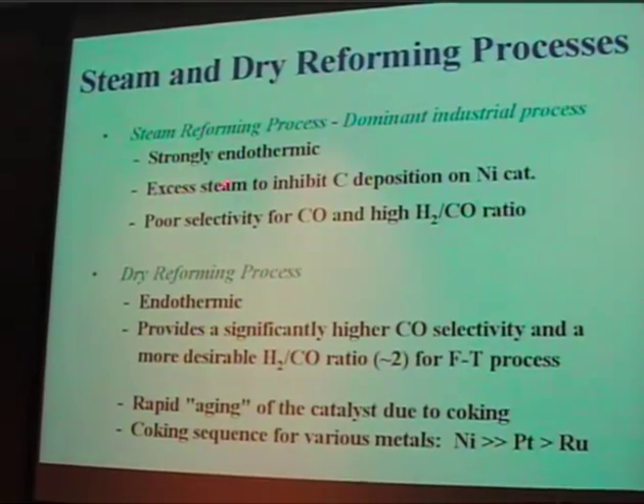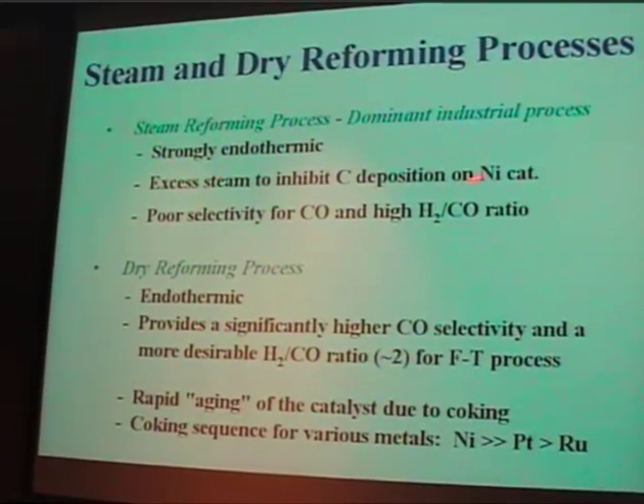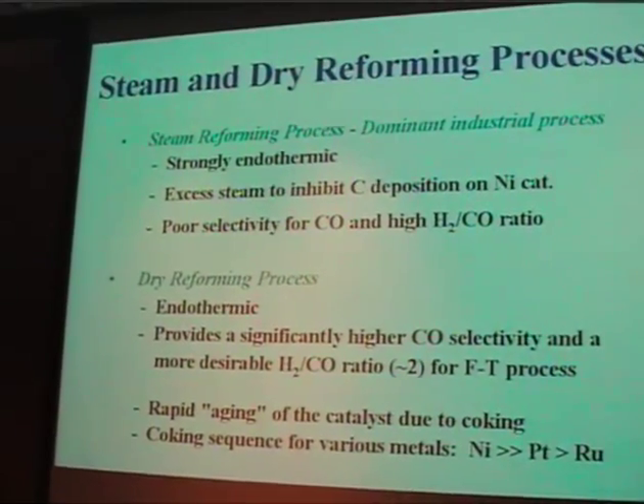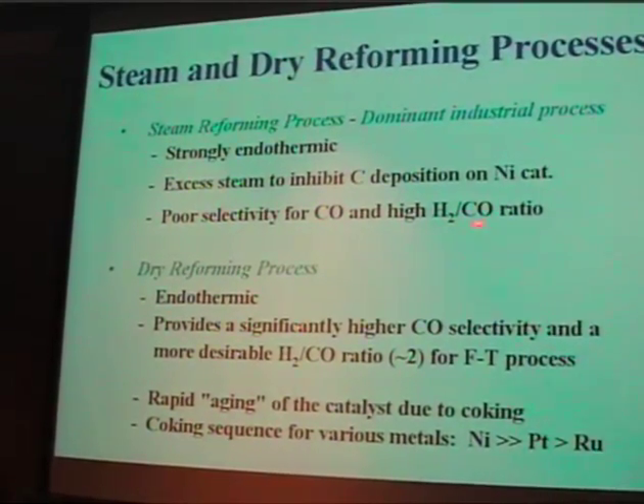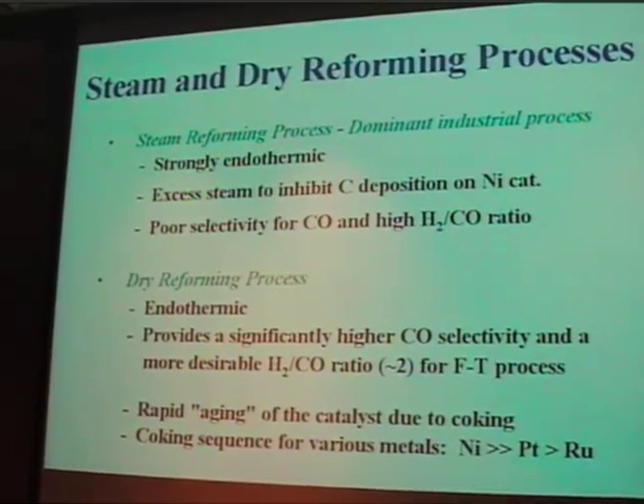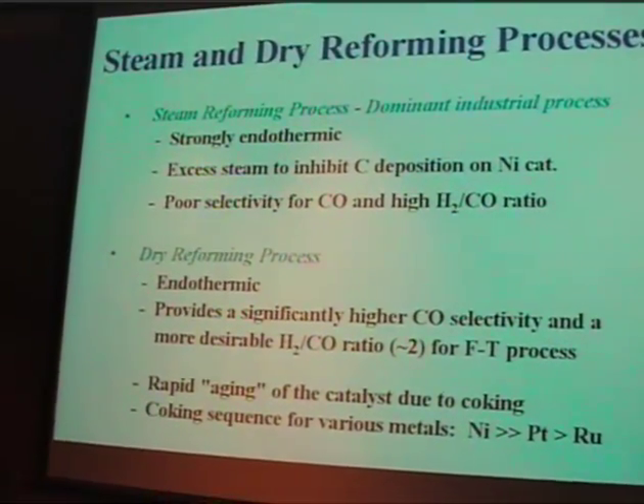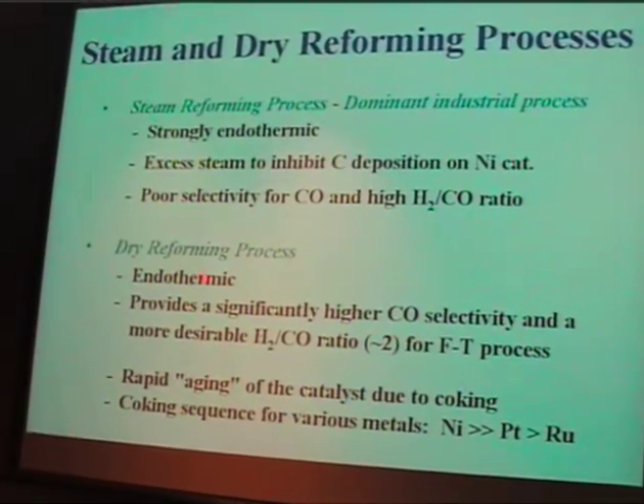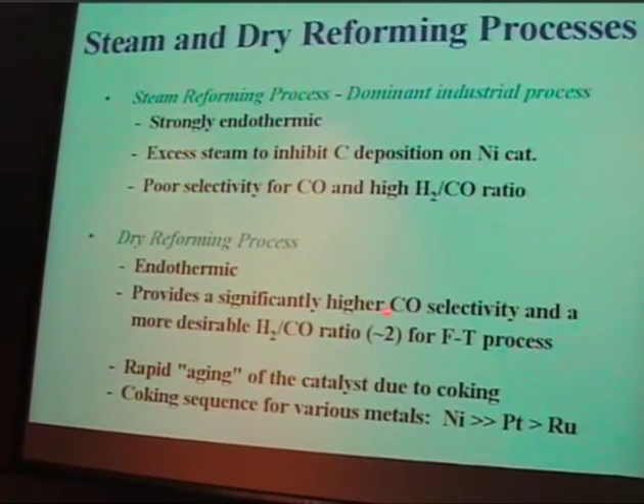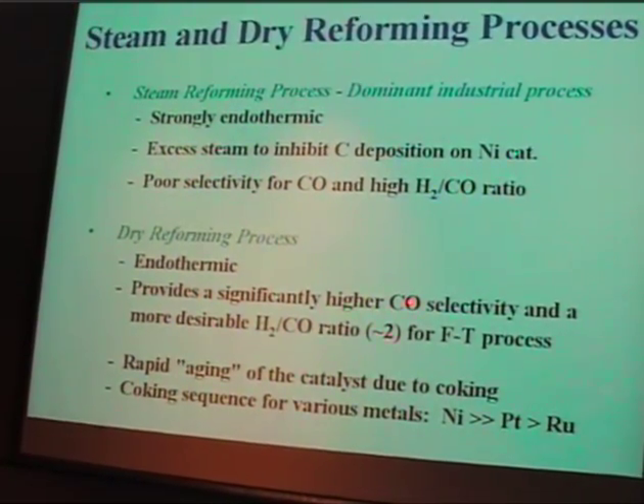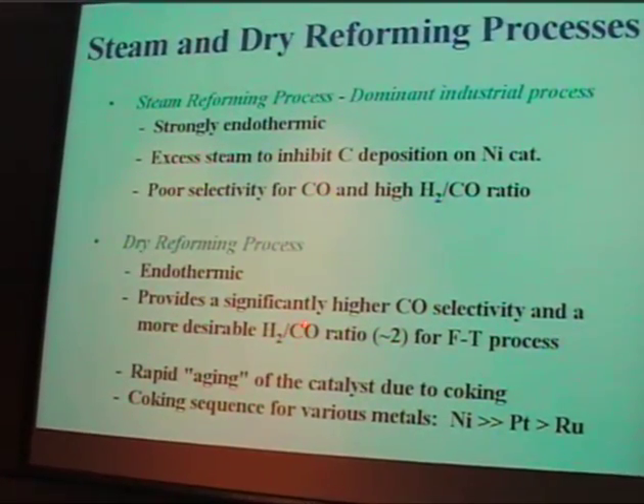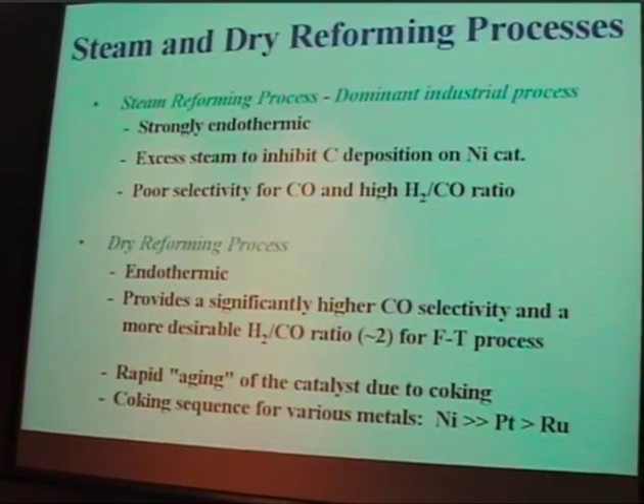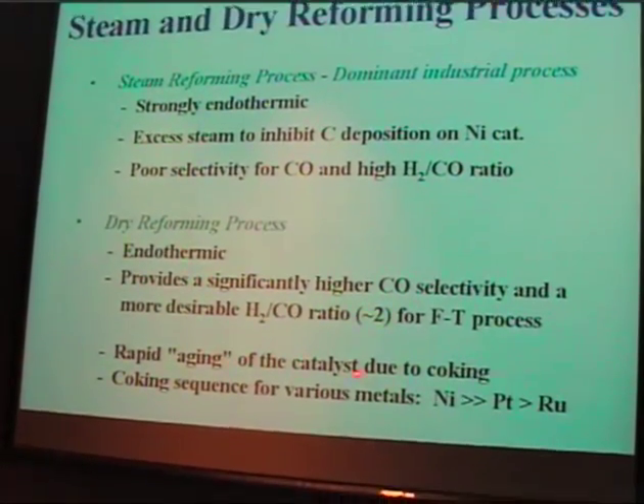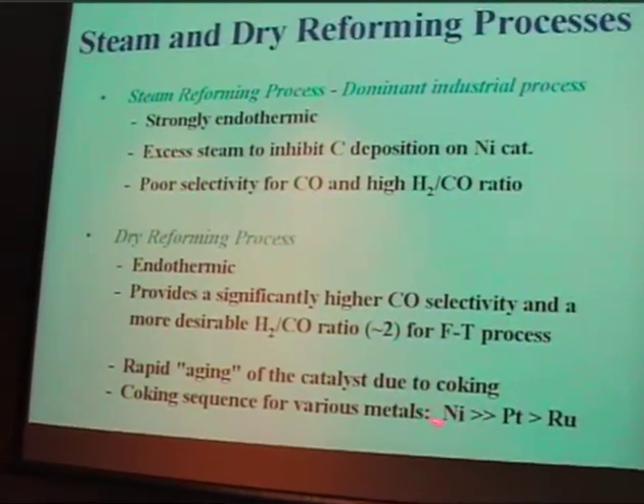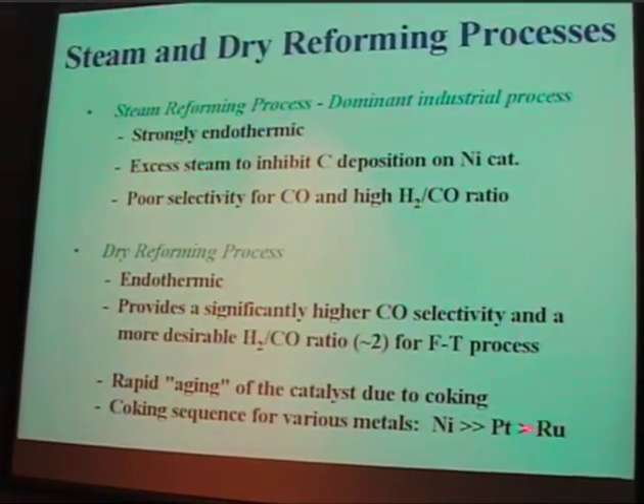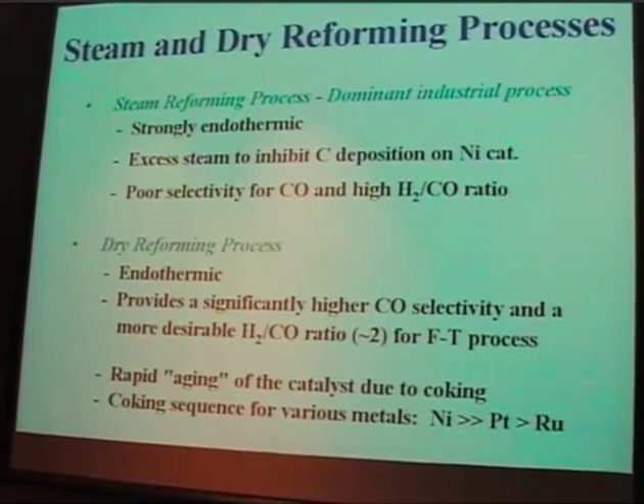Another problem with steam reforming is that you can build up quite a bit of carbon with a nickel catalyst, and you don't have necessarily the hydrogen to CO ratio that one needs for the Fischer-Tropsch. Lower selectivity. The dry reforming, as we mentioned, it's endothermic, so it's going to cost you energy. But it's higher CO selectivity, and then you are getting the ratio that you want. It can suffer again from rapid aging due to coking. And since our initiative was to look at the non-group 8 metal catalysts, nickel would be problematic.